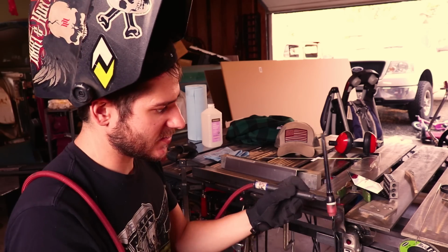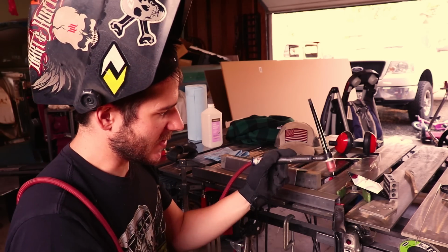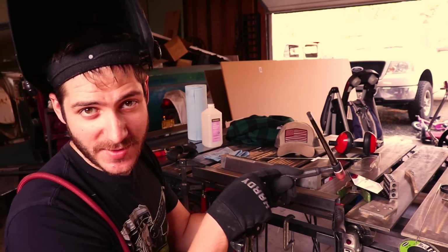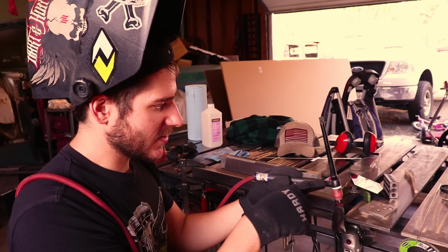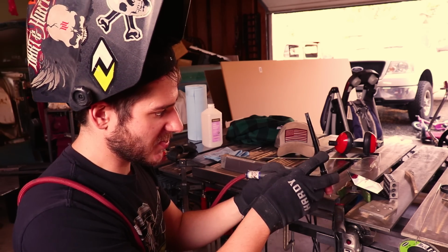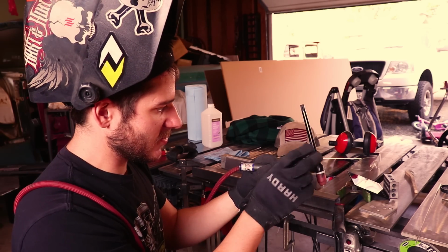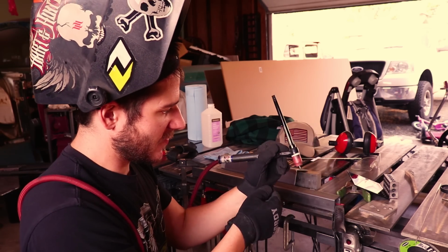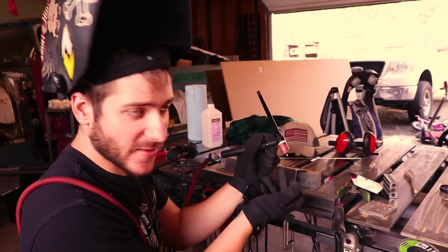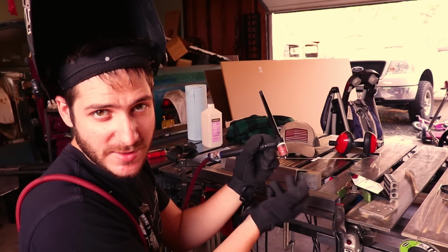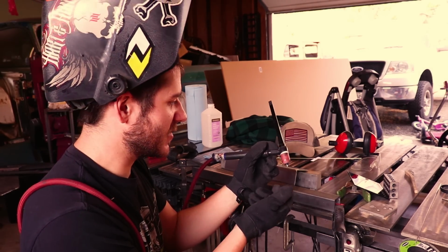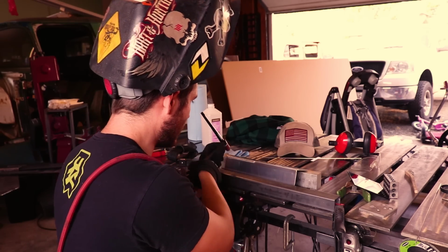And then if I'm doing aluminum, I try and hold it as far back as I can, especially on an air-cooled one, because this will get super hot on an air-cooled. On a water-cooled, it'll stay perfectly fine, but if you're this close, your hand's still only this far away from aluminum, and you're usually running 200, 250 amps, and so that gets hot fast.